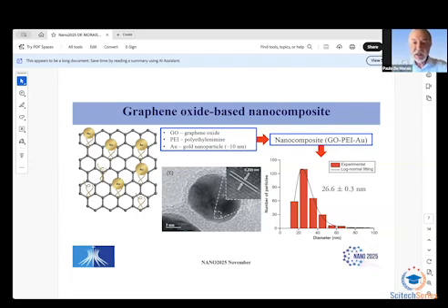And of course, we performed all the materials characterization. For instance, in the middle, you can see a high resolution transmission electron microscopy image of the gold nanoparticles. It emphasizes the interplanar distance typical of gold, about 2.35 angstroms or 0.235 nanometers. On the right-hand side, you can see a result of the transmission electron microscopy of the nanocomposite itself. The typical size of the nanocomposite is given by this histogram. The mean size of the nanocomposite is about 27 nanometers.